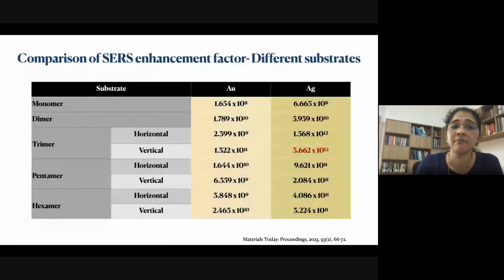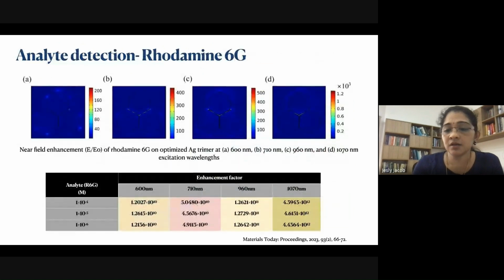And again, when we compare the results and the SERS enhancement factor, we can see that the trimer, pentamer and hexamer are the best performing compared to the monomer and dimer. And among them, the trimer vertical arrangement shows a very good enhancement factor, up to the range of 10^22. And we have analyzed how it detects an analyte. For that we have chosen rhodamine 6G. This is a common analyte used in biotechnology for SERS studies.